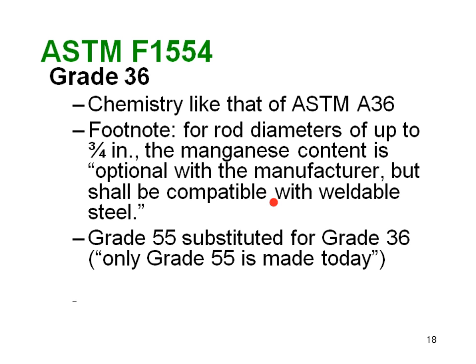However, there's a footnote, and the footnote says that for rod diameters up to 3/4 inch, the manganese content is, quote, optional with the manufacturer, but shall be compatible with weldable steel. Now remember, when we said weldability, we did not define that in terms of whether you could or could not weld the material. We decided it had to do with the relative ease with which you welded the material. Now, this definition in the footnote talks about weldable steel. It doesn't talk about how easy it is to weld it. And frankly, I'm not sure what it means that the manganese content shall be compatible with weldable steel.